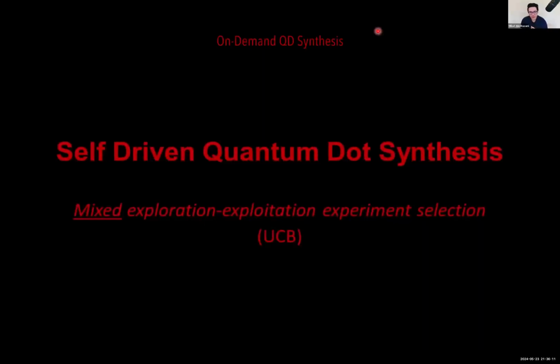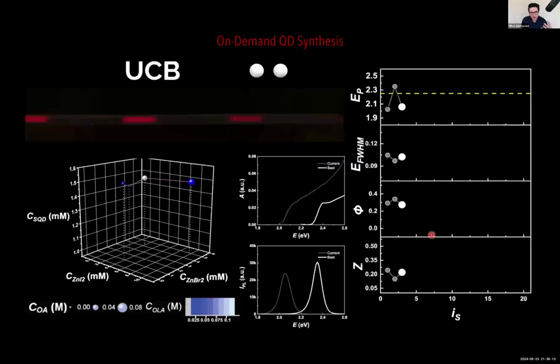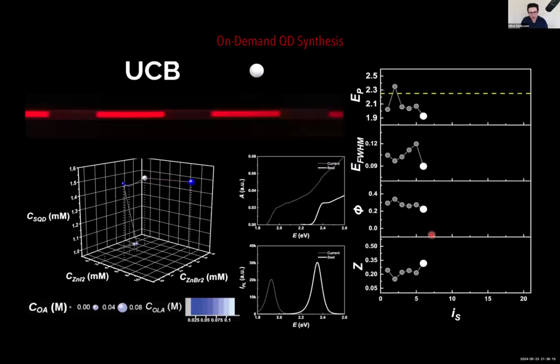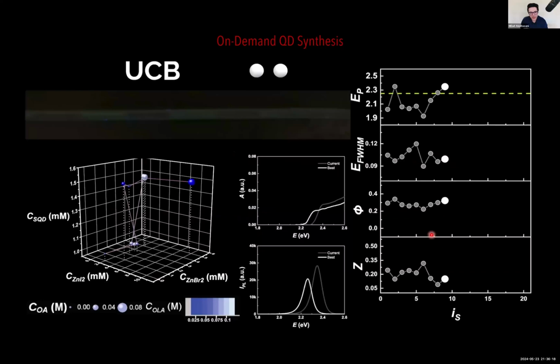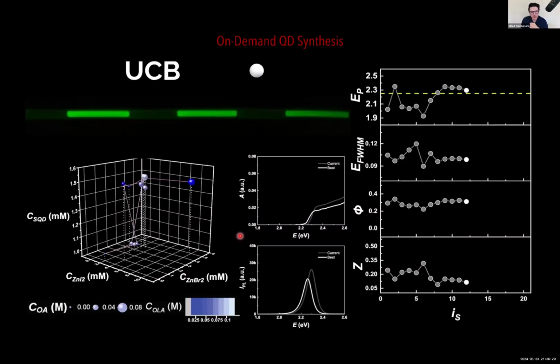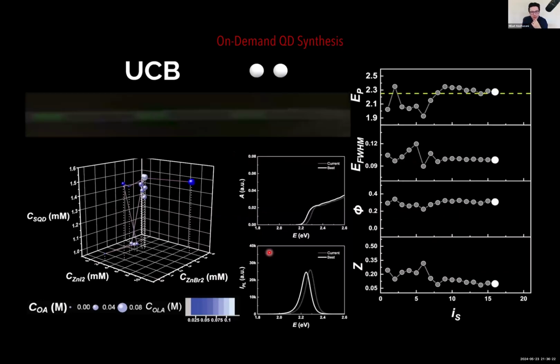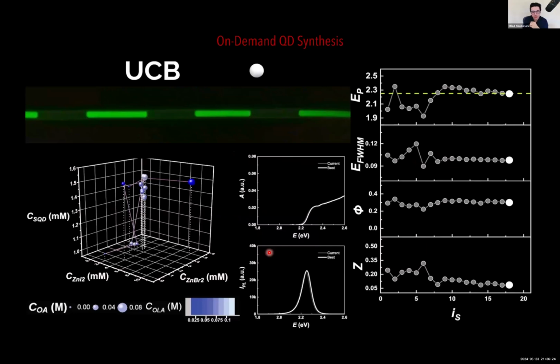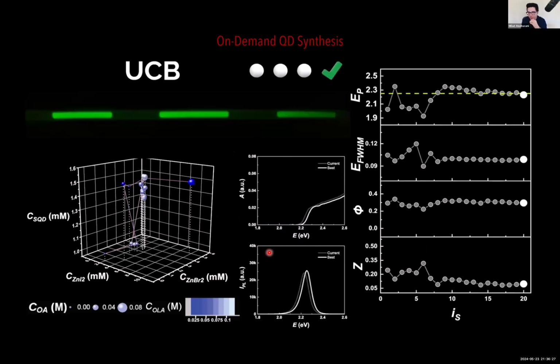Here's a video of the artificial chemist searching through a 6-dimensional input, 3 outputs space, and it's trying to find the synthetic route of the best green emitting quantum dots, starting with no prior knowledge. So this is just a black box. Within 15 experiments or 90 minutes, they could find the synthetic route of the best green emitting quantum dots. And if you actually archive your external data and provide access to the prior data, you can go from 90 minutes to only 10 minutes.